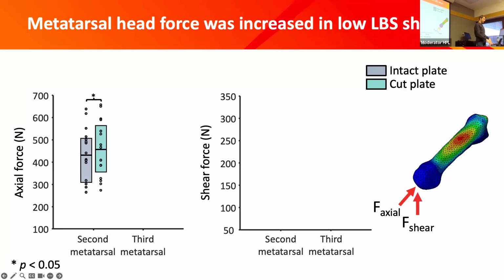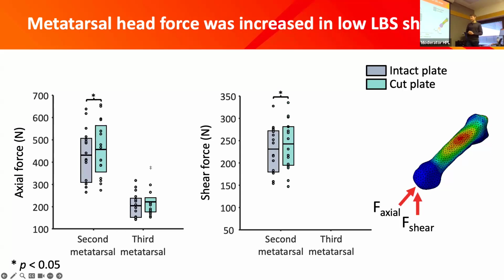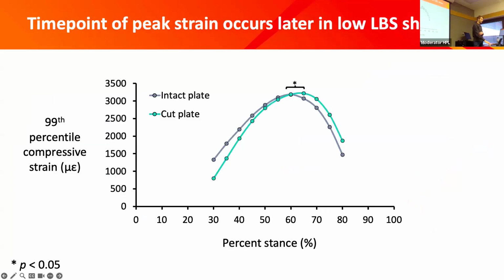We did, however, see significant increases in axial force, so the force that was applied to the metatarsal head in the axial direction in the second metatarsal. We didn't see any change in the third metatarsal, but there was a trend for an increase. And we also saw a significant increase in shear force acting on that metatarsal head in the second metatarsal. So for both these two cases, the cut plate condition had significantly higher shear and axial force applied to that second metatarsal head. Same news for the third metatarsal here. It was a trend for an increase, but not significant. So this is kind of confusing. We saw no change in strain, but we saw this increase in axial force applied to the metatarsal head.